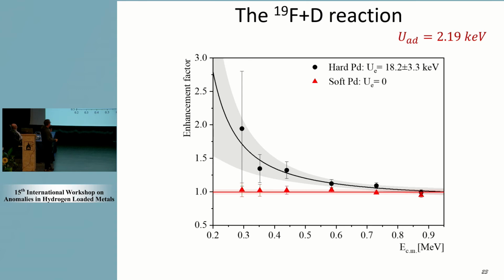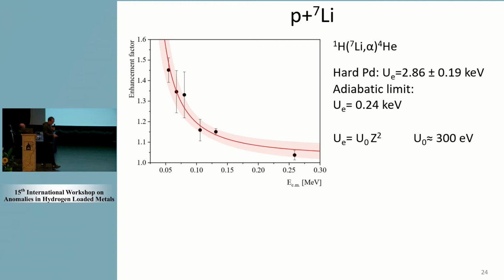So just by changing the structure of the palladium target, we increased this electron screening potential by almost an order of magnitude above the adiabatic limit. Then to check a little bit on the Z dependence of electron screening, we also studied lithium on protons in inverse kinematics. So now we knew that in the soft palladium, there was no electron screening. We just divided the yields of the two targets, and then we could determine the electron screening potential in hard palladium, which is 2.9 keV, again more than an order of magnitude above the adiabatic limit.